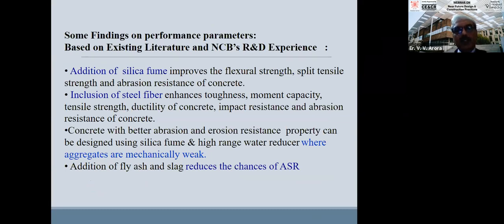Some findings, in summing up, on these specific materials for high performance: addition of silica fume is a summary of what I have said earlier. It improves flexural strength, split tensile strength, abrasion resistance, and impact resistance. And inclusion of steel fibers enhances toughness, moment capacity, tensile strength, ductility, impact resistance, and abrasion resistance of concrete. Concrete with abrasion resistance property can be designed using silica fume, high-range water reducers, where aggregates are mechanically weak, addition of fly ash, and a higher grade of concrete used in combination with these materials really produces a high-performance concrete. Because if our grade is low, then even if you add these materials, you will not be able to achieve a high-performance concrete. That also has to be kept in mind.